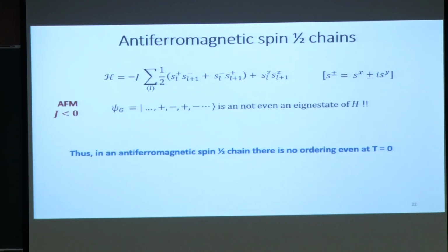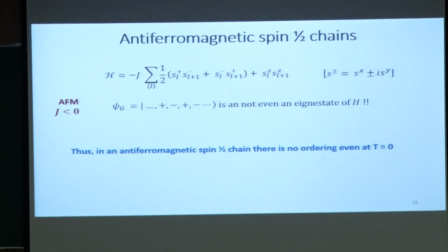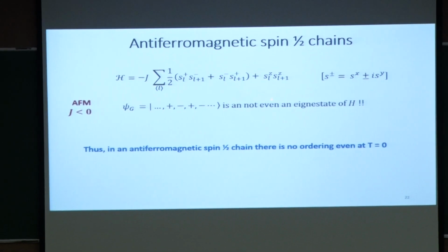But if you go to an antiferromagnetic case, if you prepare a state where the spins are up, down, up, down, up, down, then you would see that this is not even an eigenstate. The reason for that is, if you write it in terms of ladder operators, this term in your Hamiltonian, which is known as the transverse term, basically flips the spins, and because of those spin flips, you don't actually get an antiferromagnetic ordering even at t equal to 0 in a spin 1/2 chain. So I hope this distinction is clear to you. In a ferromagnetic case at 0 temperature you get all spins up, but in an antiferromagnetic case you don't get up, down, up, down, up, down. Why? Because this transverse term tends to disrupt this ordering.